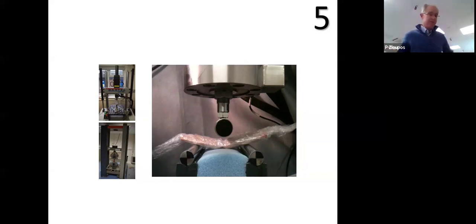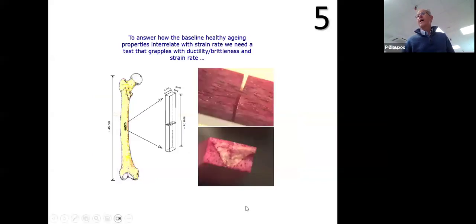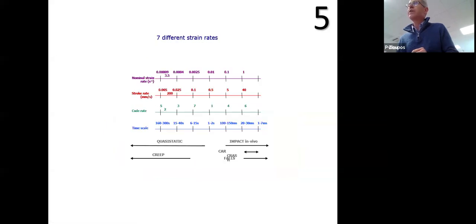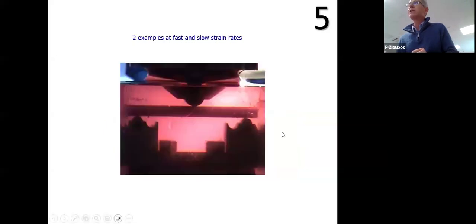So what I'm saying is that the study of bone and the mechanical effects of bone, or what bone demonstrates, it's always contextual. And the context in this case is, what are the environmental conditions, the boundary conditions? What is the strain rate, right? So how do we examine this at the bone material level? Well, by actually producing samples from a femur, let's say, which are very small, matchstick size. So let's do the same experiment and look at how bone behaves, not as a whole bone, but as a small sample. Various strain rates. Let's see, that should play.